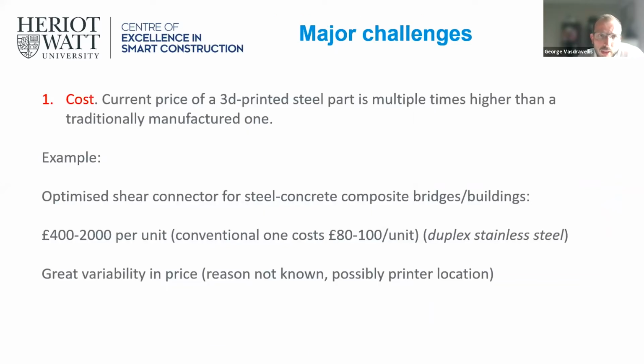Now, major challenges, I would say, in terms of money, of course, are the cost and the long time. The current price of a 3D printed steel part is multiple times higher than a traditionally manufactured one. Just as an example, I took some quotations for a potentially 3D printed optimized shear connector for steel-concrete composite bridges and buildings. The prices I got from various companies range from 400 pounds to 2,000 pounds per unit, compared to the conventional one, which costs about 80 to 100 pounds per unit. This is a duplex stainless steel optimized shear connector.